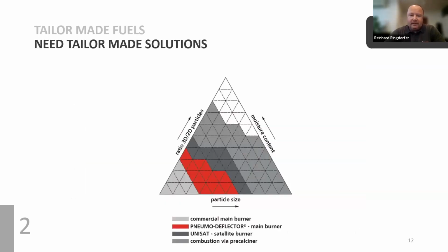We have made this small diagram where you can see the ratio of the 3D to 2D particles, the moisture content, and the particle size. And you can see there is basically a very small section which can be used in a normal kiln burner through the main burner itself. We have made several inventions or devices for the secondary fuel channel in the burner since more than 20 years now, to influence the behavior of the particle coming out of the burner. The last invention is the Pneumo-Deflector, which is also in use for more than 10 years now. I will go to that a little bit later.